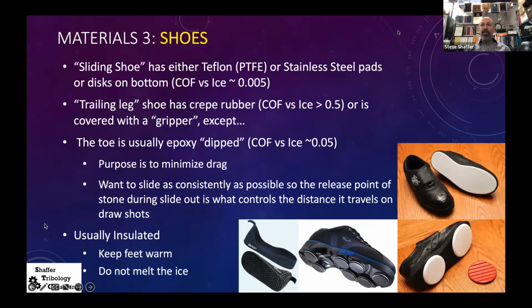The third material is curling shoes. You have two shoes. You have a sliding shoe, as you saw in the first video. You're sliding out with one foot, you're squatting on that one, and the other foot's trailing behind you. The sliding shoe's got either Teflon, most shoes have Teflon on the bottom, or the really good curlers may have stainless steel pads on them. These are either pads or discs, and the coefficient of friction is very low, 0.005, sort of on the order of what we saw for the stone and the ice.